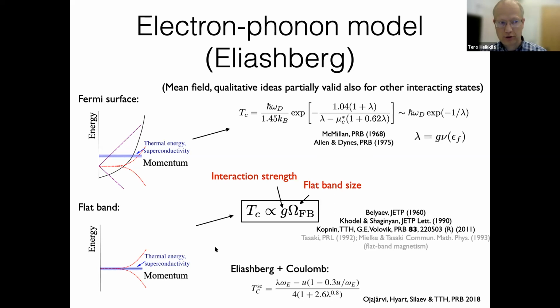You can do the same for flat bands and you get this linear dispersion, but once you include the Coulomb interaction at large lambda, you also get some corrections. But now these corrections rely on the self-consistent Born approximation only, which might not be valid anymore for large lambda. But the bottom line is that for small lambda, you get this linear dependence on lambda.